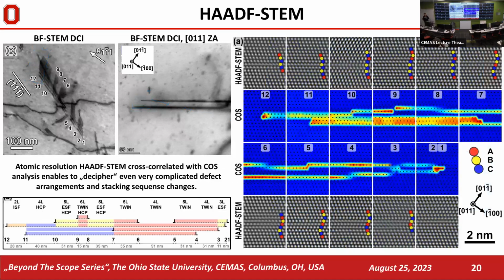Now, when we take a look at the analysis of the whole package of the whole twin embryo, on the left, this is what you would classically see with CTEM DCI. This is how you would analyze such a defect structure. You would do g·b, you would do tilting, you would be looking for a change in the stacking fault ribbon. That's how you would be trying to find a description of this defect. But using STEM, using these advanced tools, we can go further in depth, and we can analyze